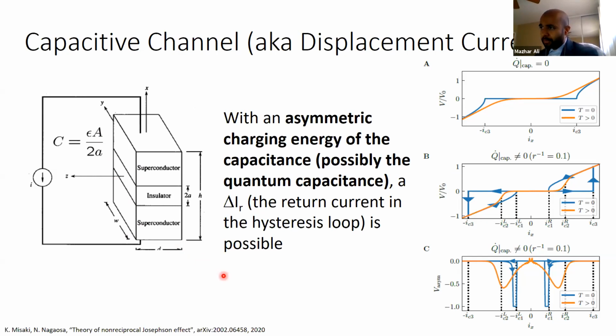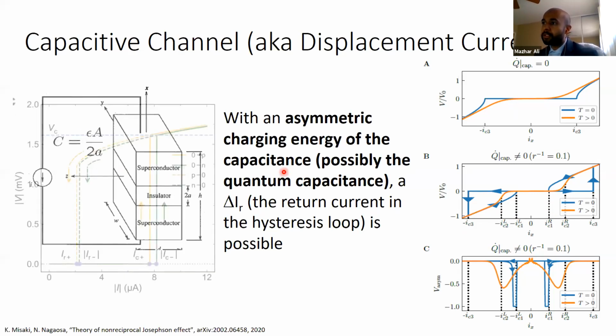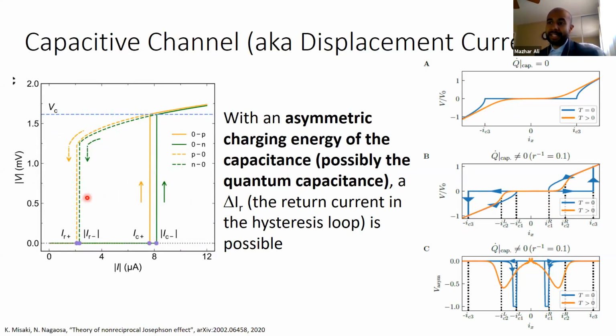But the derivation of what could cause a non-reciprocal effect that they explain is that if you have an asymmetric charging, again, left does not charge the same as the right. So plus voltage charges the capacitor differently than minus voltage. If that happened, then you could end up with a delta, not IC, but they talk about a delta IR, the return current. So on the inside of the hysteresis. So that's interesting. There we go. So, maybe we even see that.